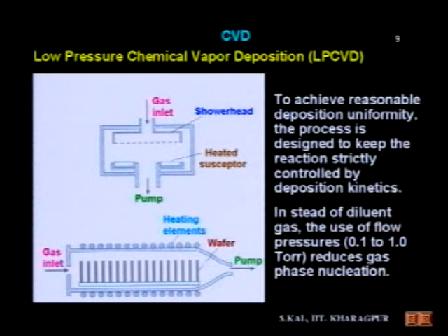If the pressure inside the chamber is made low, of the order of 0.1 to 1 torr, in that case the nucleations will be reduced, and those nucleations, we have seen, will put particulate contamination inside the film, and they will cause contamination or particulate formation, which are other defects in epitaxial growth as well as in polycrystalline silicon growth. Okay, so now